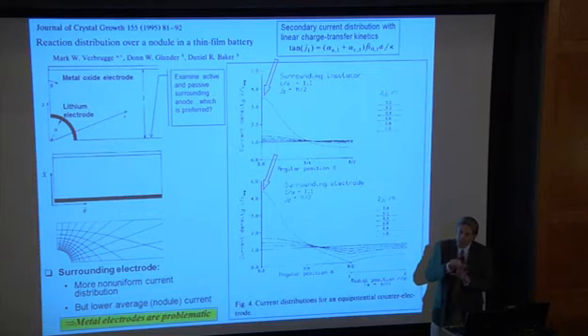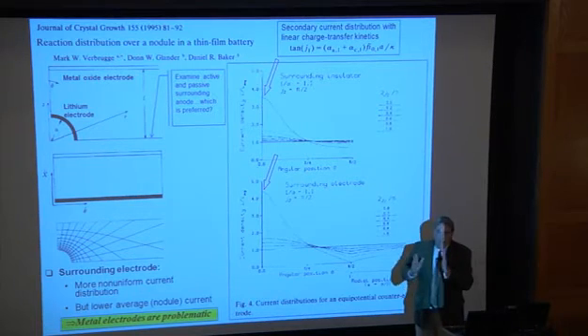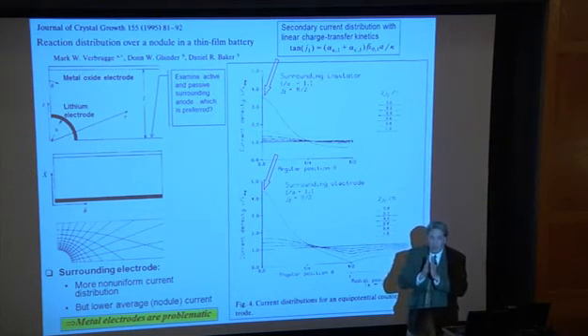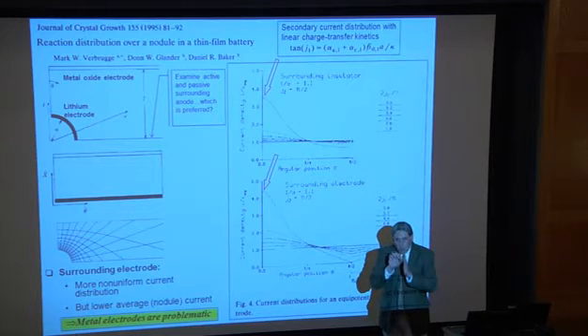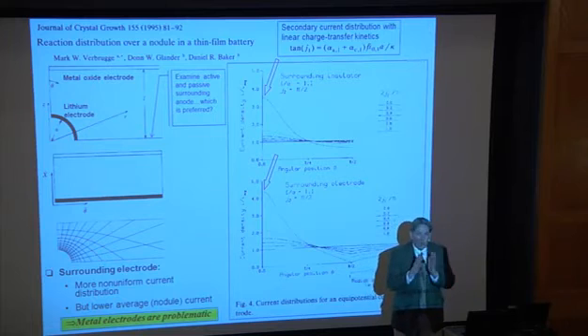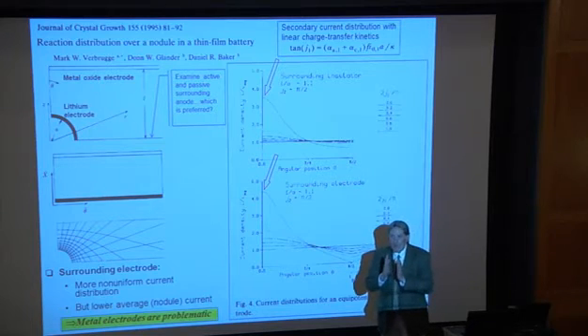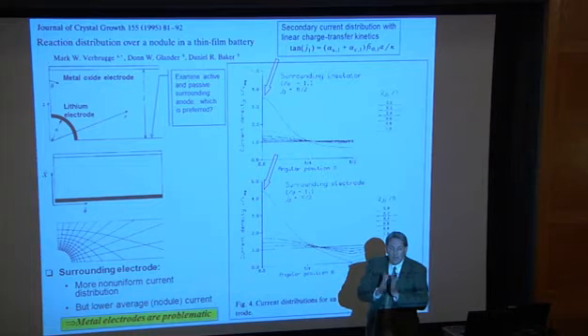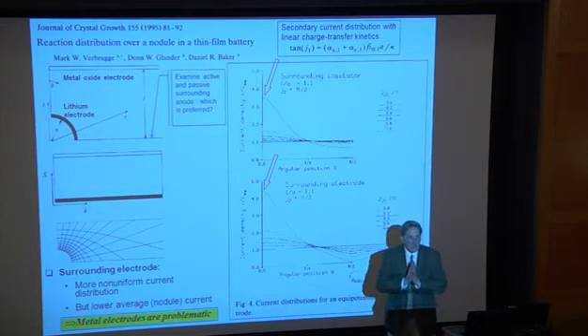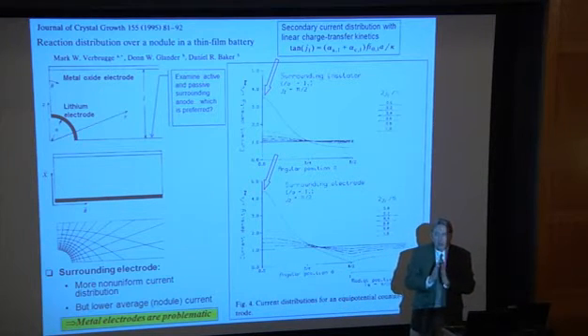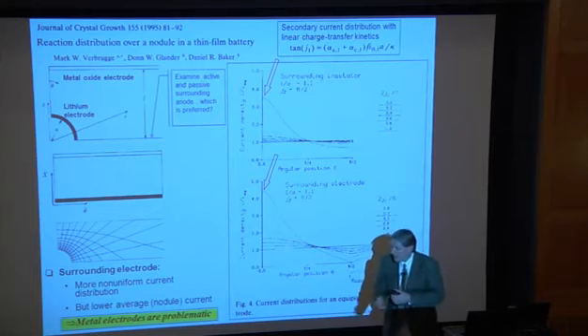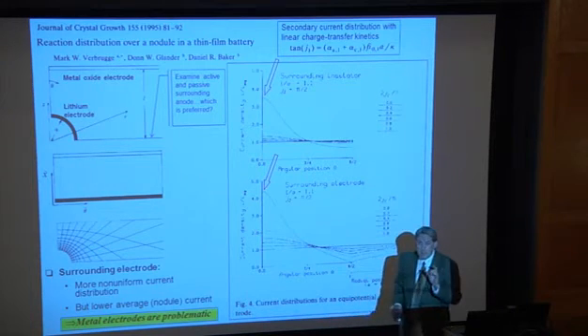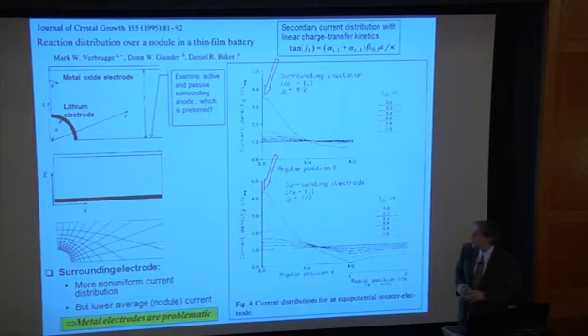If you have a protrusion, like on a metal electrode, and you bring your electrodes closer together, you will focus more growth on the tip of that protrusion. You exacerbate dendrite growth or nodule growth. And for that reason, there is a paradox out there that the more you push your electrodes together to get a thin film, the worse it is for your shorting by metallic shorting across the cell. And that's something that will always be a challenge for a lithium metal electrode in particular.